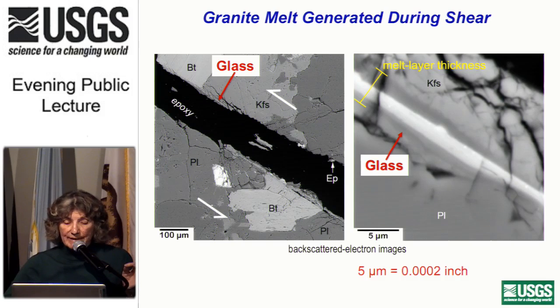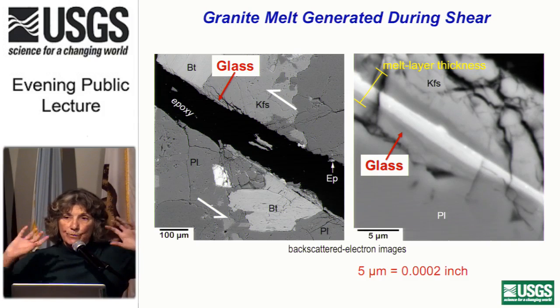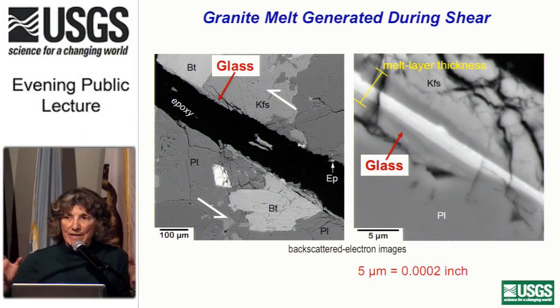So the melting points of the two feldspars are about 1100 to 1200 degrees centigrade, whereas the melting point of quartz is rather higher, at about 1600 degrees. Although if you very finely grind up a mineral, it will melt at a somewhat lower temperature.